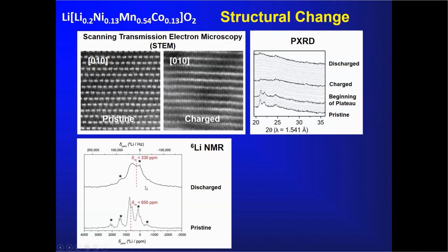And here's some lithium-6 NMR of the pristine material, and after one cycle. The key point here is the center of gravity of these lithium signals, these are the spinning sidebands with the stars, has changed on discharge. So you remove the lithium ions, you put them back in again to the structure, but the lithium environment is different at the end of discharge compared with before charge.